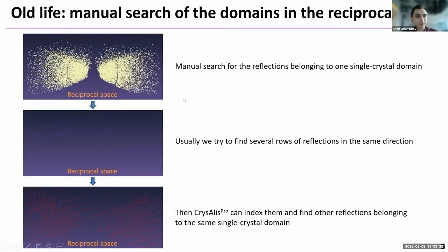So usually during the rotation of the initial cloud of reflections in the reciprocal space, we try to find several rows of reflections in the same direction by eye. And once we find 3 lines, CrysAlis can index them and find other reflections belonging to the same single crystal domain. But of course, such a manual procedure can require a lot of time. And of course, we cannot manually find, for example, 100 domains. That's why we can miss something.